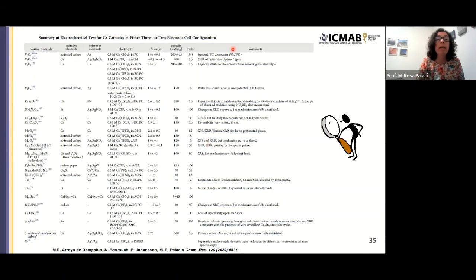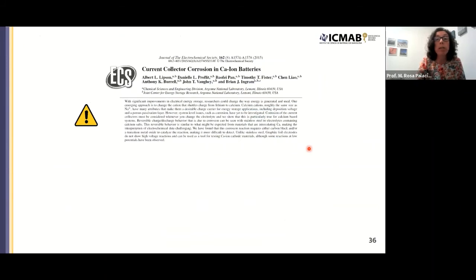This is a summary, from a review that we wrote recently about calcium batteries, of all publications reporting potential cathodes. Be critical when reading those papers, because in some cases no complementary characterization techniques were used, and then the authors were misled by the response, which may be due to side reactions. As for instance, here you have a paper reporting that what they see is the current collector corrosion. So as simple as that.